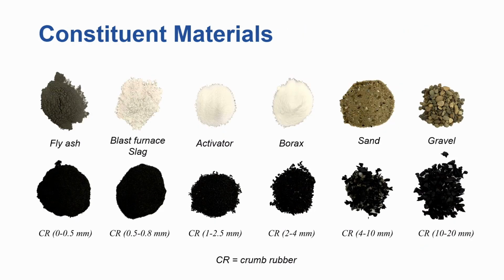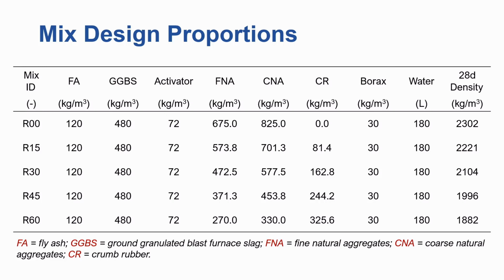So these are the constituent materials that I've used in my PhD research. So the cement replacements include the fly ash, blast furnace slag, and a chemical activator. In my case, I've used sodium metasilicate anhydrous. And then we added another chemical called borax just to enhance the workability of the mix and increase the setting time for this type of concrete. Then there was the sand and gravel, and we used 6 different sizes of rubber particles just to ensure an optimum gradation of rubber. And then we initially tested 5 different mixes.